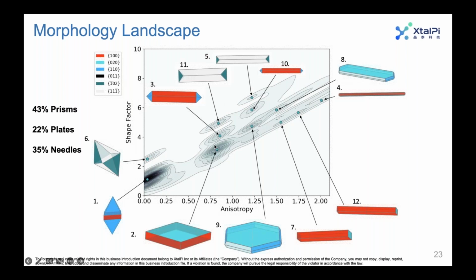Yeah, so the contours on the landscape are calculated with a kernel density estimator, and that's based off the two descriptors that we use, the anisotropy and the shape factor. In terms of error, I don't know that there are any error bars specifically associated with those. So the way we do this, right, is we take the crystal structure that we're interested in, and we determine the morphologically important faces with the BFDH model. So that tells you, in this case, right, so we can see that the BFDH gives us 1, 2, 3, 4, 5, 6 morphologically important faces. And then we can vary the surface area of all those faces manually.